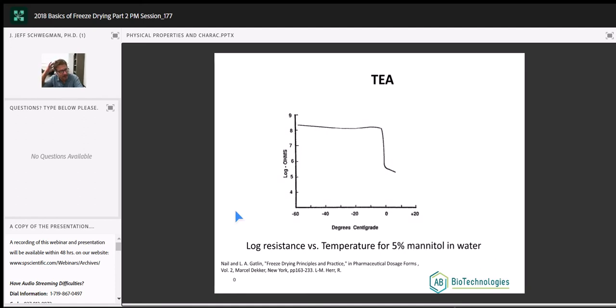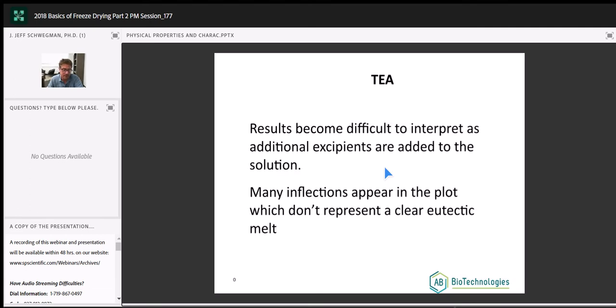So what we see here, again, the system is very good for simple formulations, one-component formulations that do have some crystallinity to them. Mannitol is not really a crystalline species, but we actually do get a pretty good response for it. So down here, the mannitol, 5% in water, frozen at negative 60. We warm, boom, we see the drop. It's very characteristic of mannitol. It's got a eutectic melt not too far below zero.